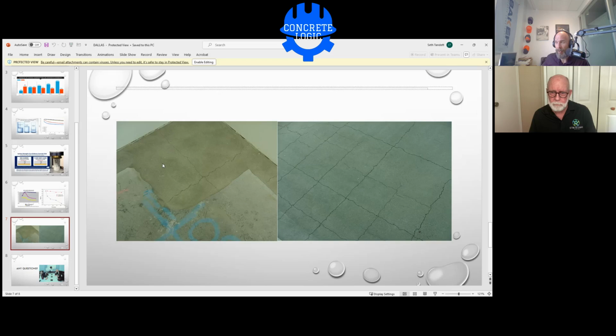It had these cracks in, you said, an 18-inch by 18-inch grid pattern throughout the slab. I believe that's a reflection of the steel reinforcement. But it shows you how dehydrated the concrete is, and it has no resiliency. You said just the 32nd, this appeared. They ground it enough to get down to the concrete past the curing compound. You can see where the paint was removed, and there was curing compound on there. Since they took the curing compound off, that's what we ended up with.